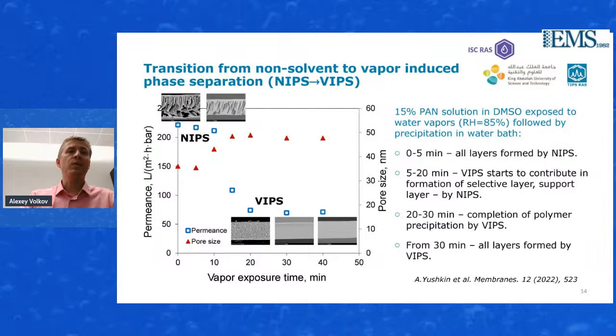If we keep quite a low exposure time to the water vapors, let's say up to 10 minutes, we then immerse the membrane into the water, and that means we don't have sufficient time to get the phase inversion in the bulk material of the polymeric solution. So the phase inversion is driven by the contact with liquid water as a non-solvent. But once we wait 20 minutes or more, the phase inversion is completed by the contact with the water vapors. That's also quite important to understand, to know how to operate our system for the fabrication of the membranes, getting a finger-like structure or a sponge-like structure by using the same composition and the same casting solution.